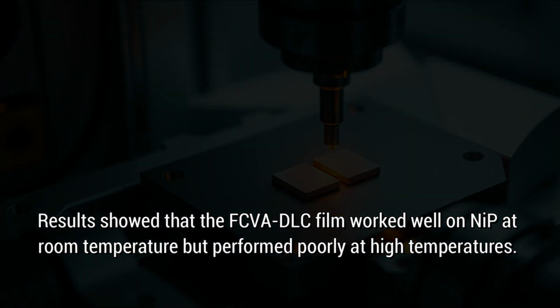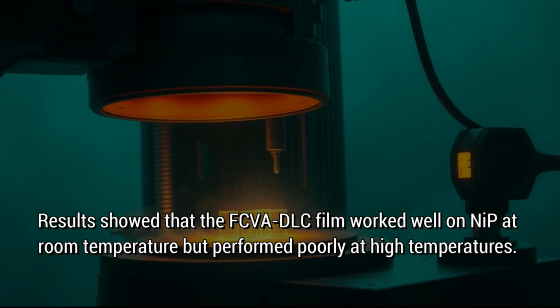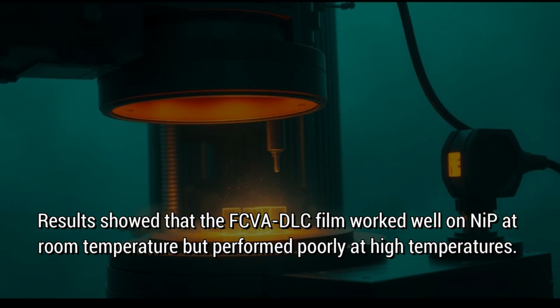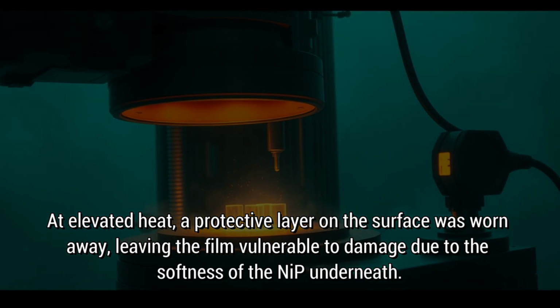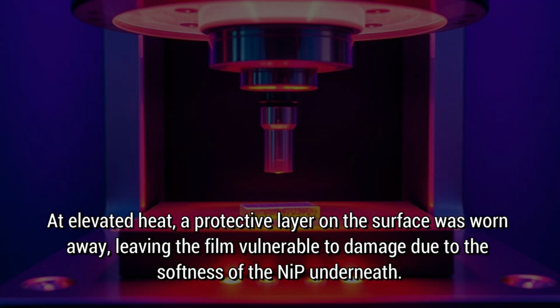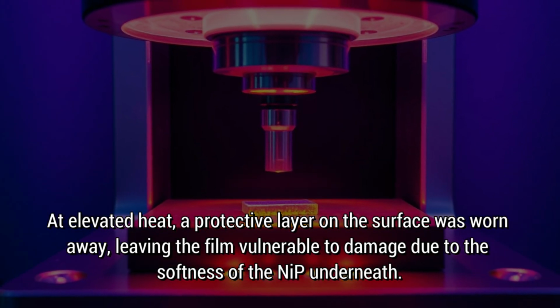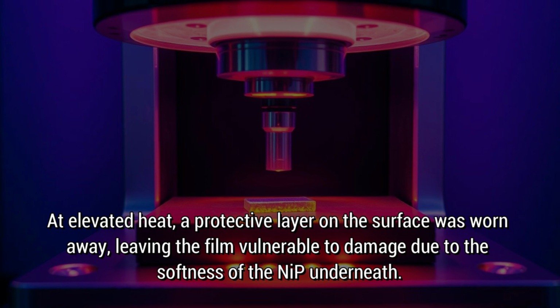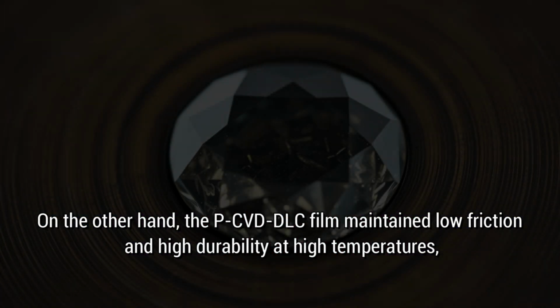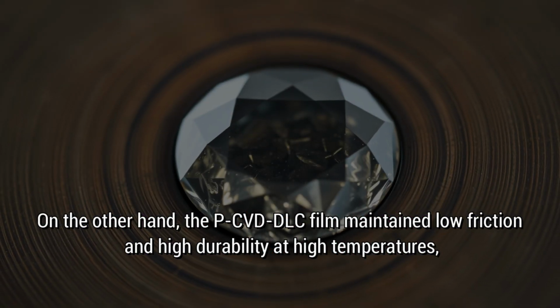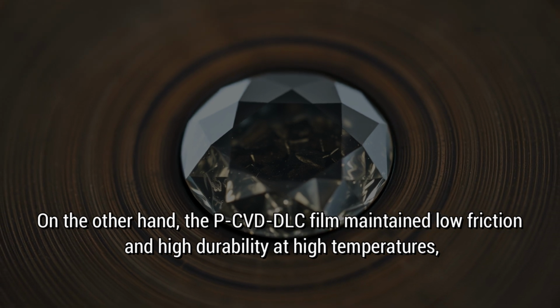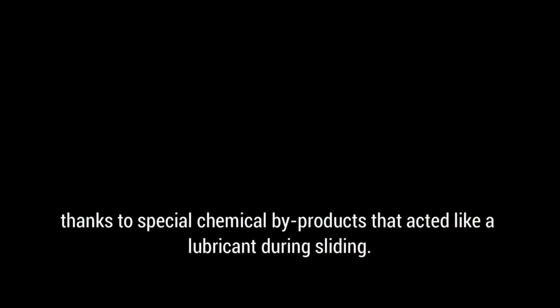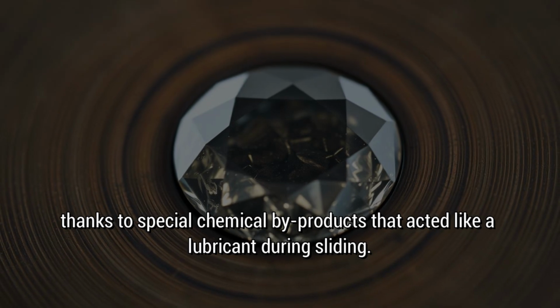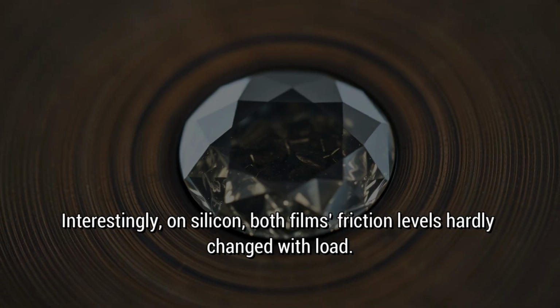Results showed that the FCVA DLC film worked well on NiP at room temperature but performed poorly at high temperatures. At elevated heat, a protective layer on the surface was worn away, leaving the film vulnerable to damage due to the softness of the NiP underneath. On the other hand, the P-CVD DLC film maintained low friction and high durability at high temperatures, thanks to special chemical byproducts that acted like a lubricant during sliding.